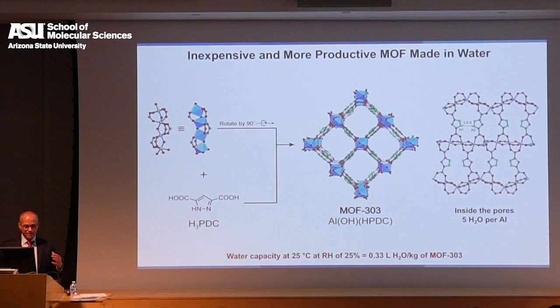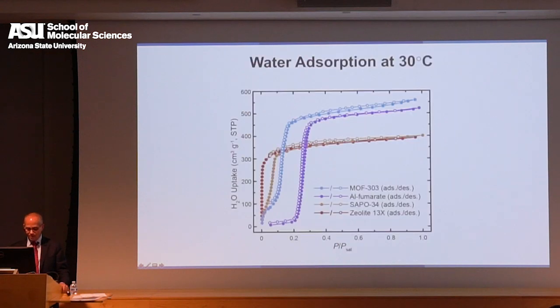So then as we published that paper, everybody said, oh, zirconium is too expensive. And that's true. And that's the nice thing about reticular chemistry, we went and designed aluminum MOF. Aluminum is cheap. O'Keeffe had already enumerated rod-based SBUs, and this is one of them, MOF 303. We designed that. It turns out to have extraordinary uptake, and it works at 10% relative humidity. And it works better than the zirconium MOF.